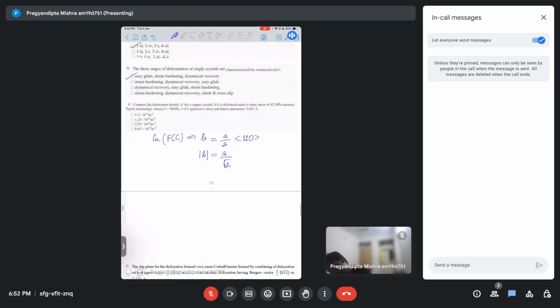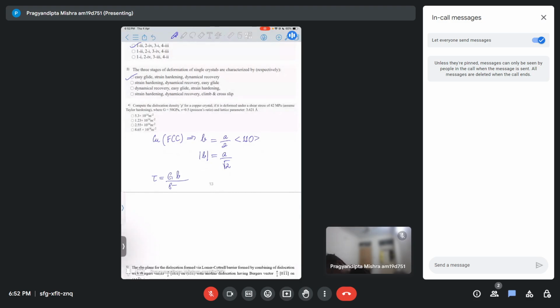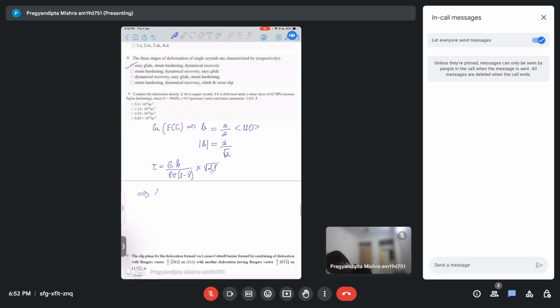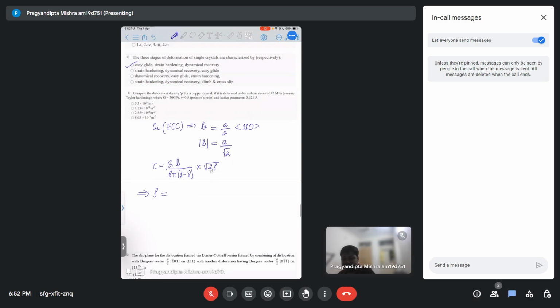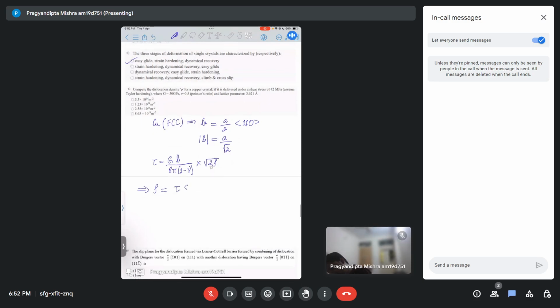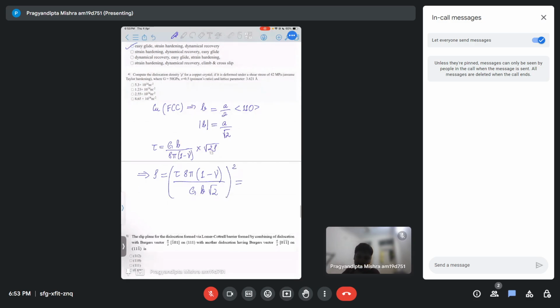So my equation is tau equal to GB by 8 pi (1 minus mu) times lambda times root 2, into dislocation density. Or I can write dislocation density equal to tau 8 pi into (1 minus mu) divided by GB times root 2, the whole square. So let me substitute and calculate the final answer. Please give me a second.